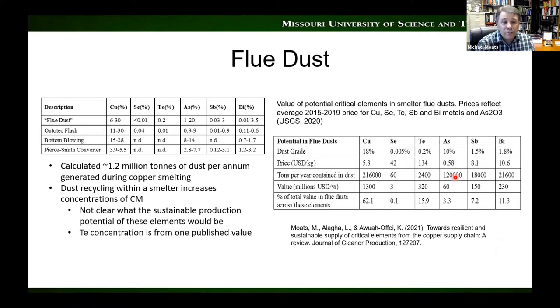Now, treating your flue dust has the benefit that you remove these elements from your refinery, which is where the problems are right now, because they tend to end up in the refinery and cause problems. So if you could remove the dust, capture the copper where the value is, and also capture your critical elements, there may be a value proposition for the copper smelter refinery. I know of some people who thought about that. There are some companies who take dust off and treat it, but typically the antimony, bismuth, and so forth are not captured. They're just disposed of.